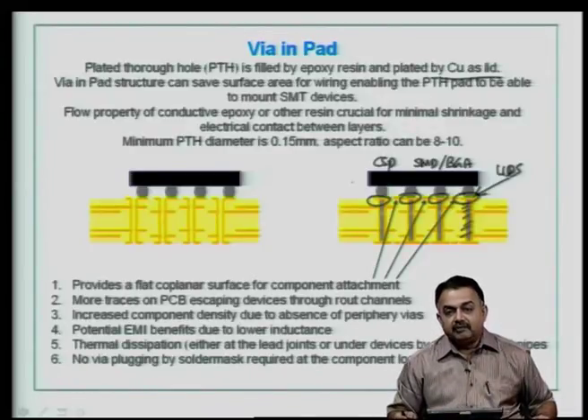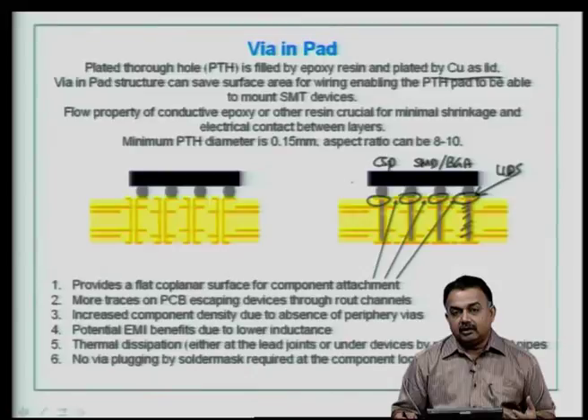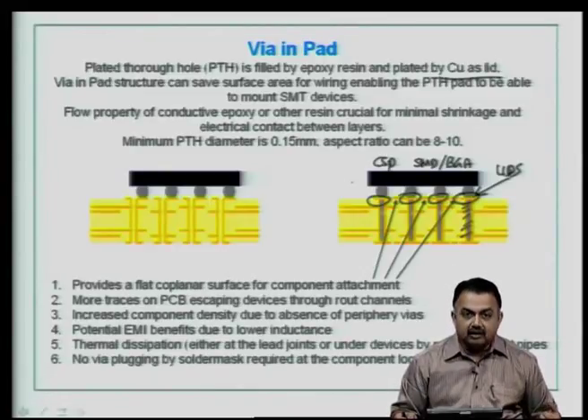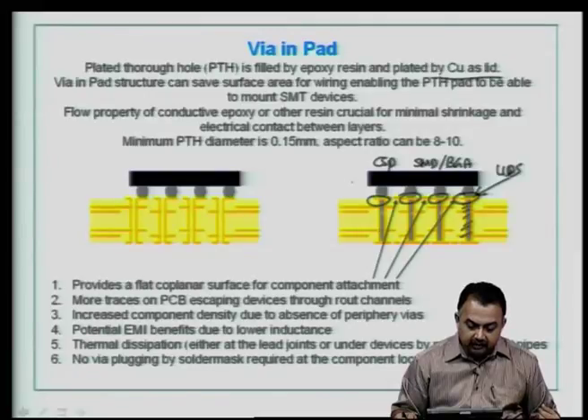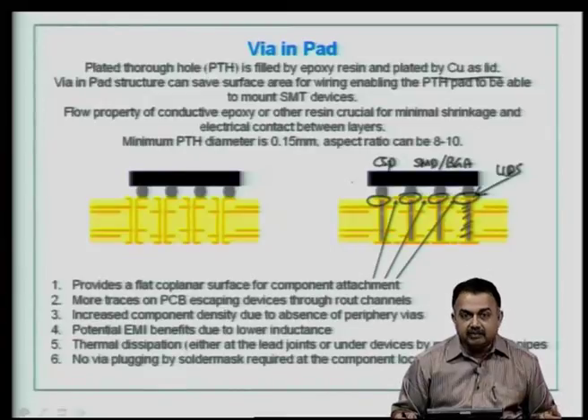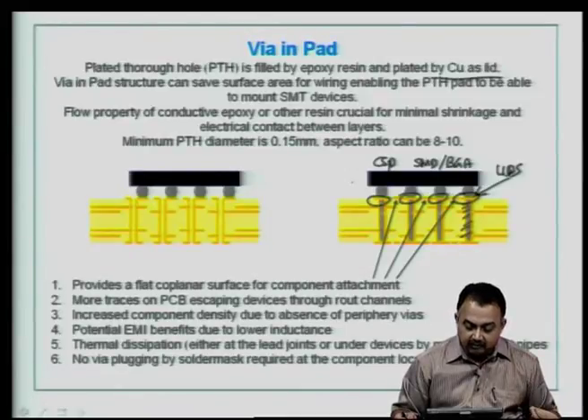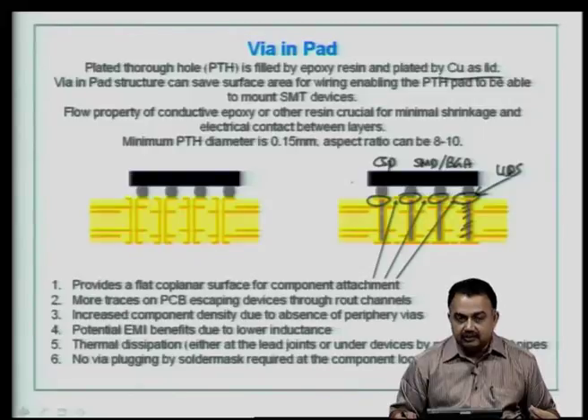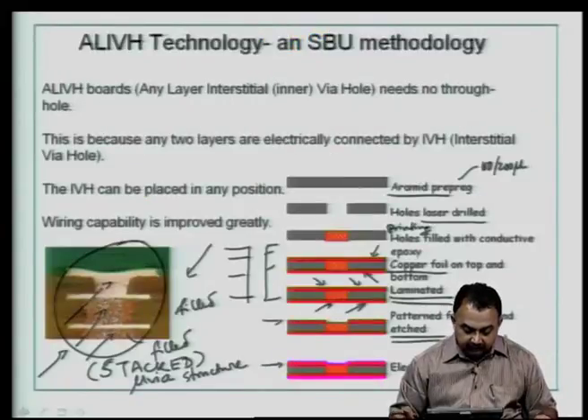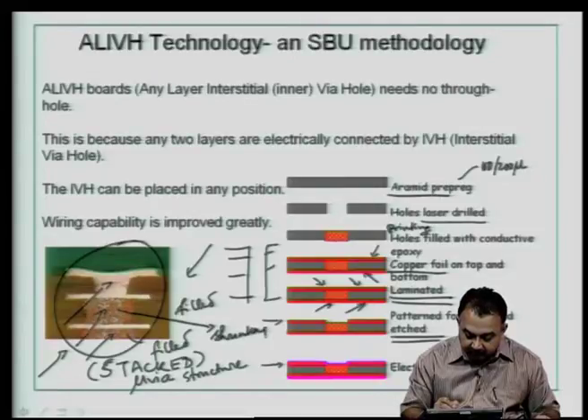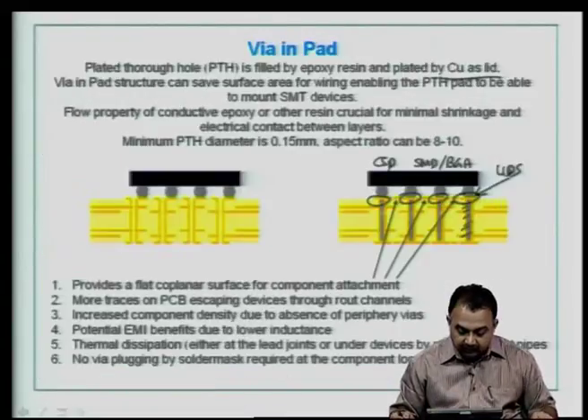So, it becomes more dense. You are not required to provide additional pad area on the surface of the board. So, via in pad structure can save surface area for wiring, enabling the PTH pad to be able to mount surface mount devices. Flow property of conductive epoxy or other resin is crucial for minimum shrinkage. Even in the earlier figure, what I wanted to emphasize here is that the material should not undergo shrinkage. So, look at the property of the conductive paste very carefully when you are using it for filling the microvia structures.